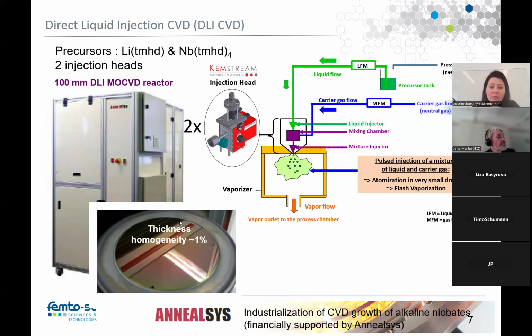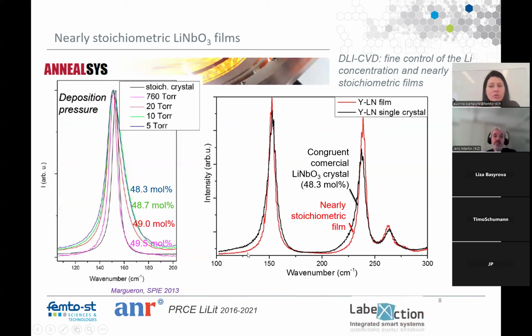As it's a CVD method, we have very nice thickness homogeneity. We also showed that we can control the lithium composition. We can tune it by changing just the ratio of the two precursors, but also, for example, by changing the pressure or other conditions, so we can tune very, very finely. And we can also make films which are nearly stoichiometric.